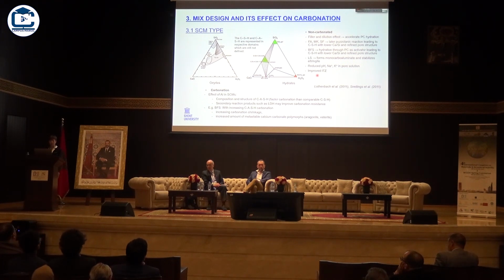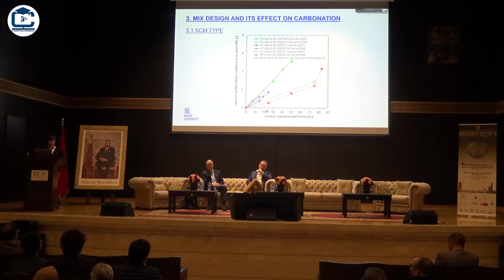Now, what is important for carbonation, which I want to add, is that if you have SCMs, it's not only that you move faster to carbonation of the CSH, but if there is aluminium present in the SCMs, you have rather a CASH gel containing aluminium than a pure CSH, and apparently this might carbonate faster than a comparable CSH. On the other hand, there are some secondary reaction products like magnesium aluminium layered double hydroxides, which may improve carbonation resistance, and this effect is not yet fully understood. It's also mentioned in literature that with this CASH carbonation, you might get increased carbonation shrinkage and also other polymorphs being formed of calcium carbonate, so not only calcite, but also more aragonite and vaterite.